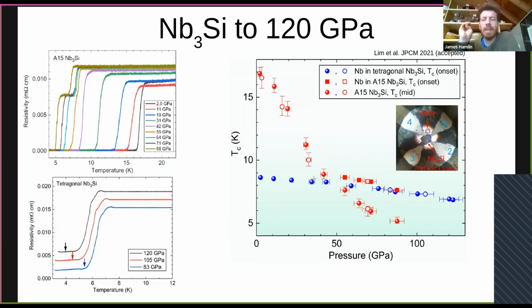Now, this A15 structure is supposedly stable above 50 GPa, so we might expect that it would convert to the A15 phase, and we would see superconductivity from the A15 phase. And if we could then release the pressure, say at low temperature, we could recover the A15 phase. Unfortunately, what we find is that that does not happen. So this lower right diagram here with these arrows show sort of where you would expect the A15 transition to be if it were there, and it does not appear.